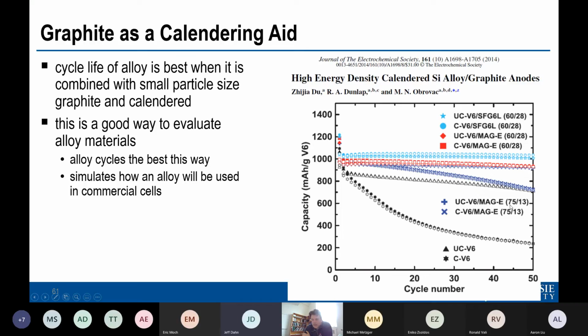good cycling. If you put less graphite in and tried to calender it, that's when you started to get this problem of there's not enough graphite as a calendering lubricant. So the minimum amount of graphite and the maximum amount of alloy was governed by how much graphite you need to obtain a high density coating. Okay, thank you. Which means that you can have more alloy than graphite, and get good cycling of the coating.